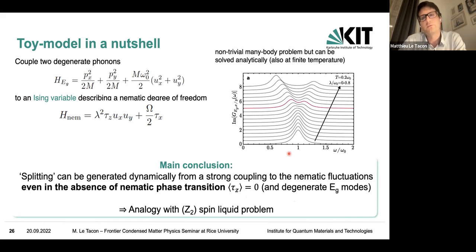And then you can compute this, and what you find is that the spectral line corresponding to the Green's function corresponding to your doubly degenerate mode can actually split if you are in a regime of relatively strong coupling, but not too strong. Otherwise, you basically induce a structural distortion. And so that splitting can obviously occur if you have a nematic order. So that means if the expectation value of your Pauli matrix tau z is 1. But again, in this strong coupling regime to nematic fluctuation, you can have this splitting even in the absence of a nematic phase transition, even if the expectation value of the nematic order is actually 0.